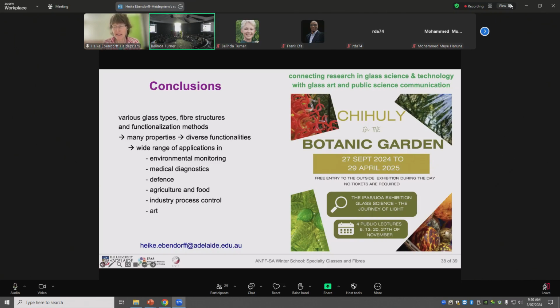Yeah. This is roughly 10 to 12 preforms, and each weighs in the order of 50 grams, so it's only 500 grams. This is the nice thing with fibers, because they are lightweight. So you can make very long fiber, and you don't need much kilogram for it. Thanks, Heike. You've got to work it out. It's 150 microns diameter, so...